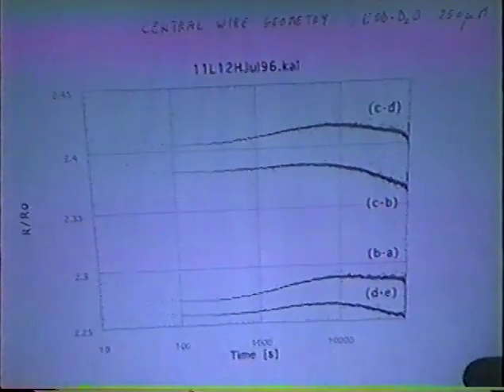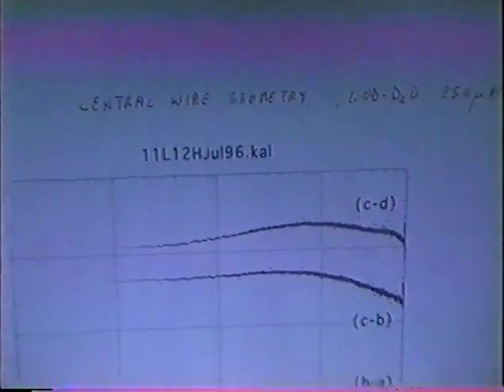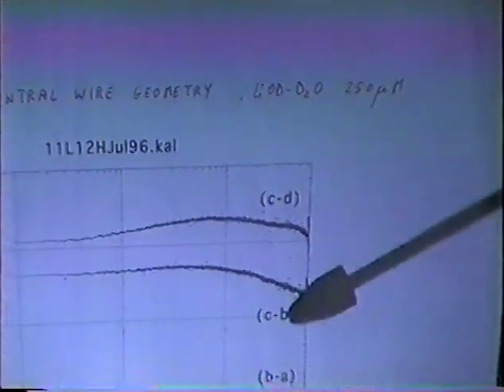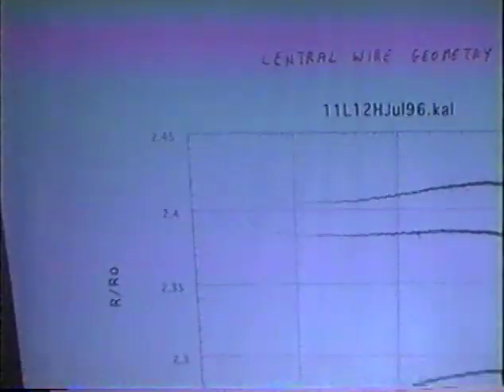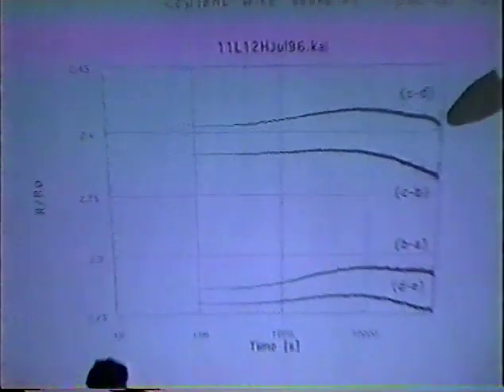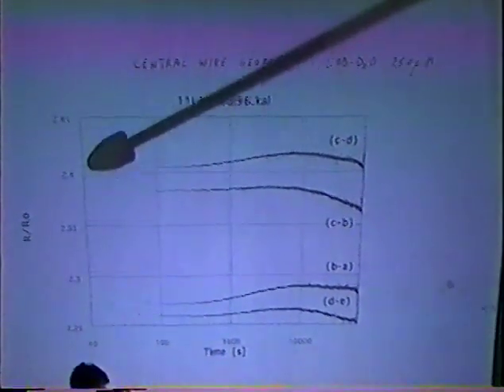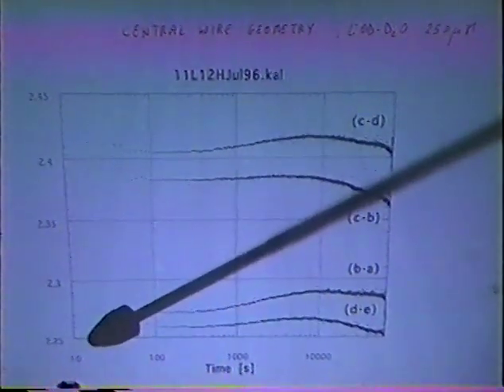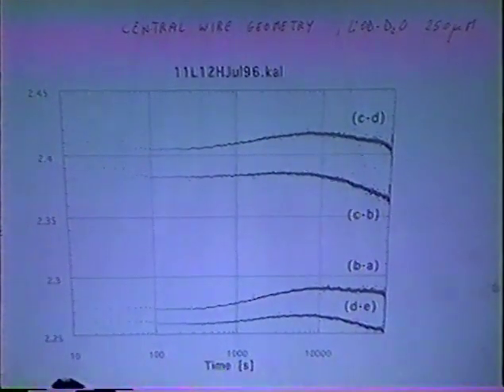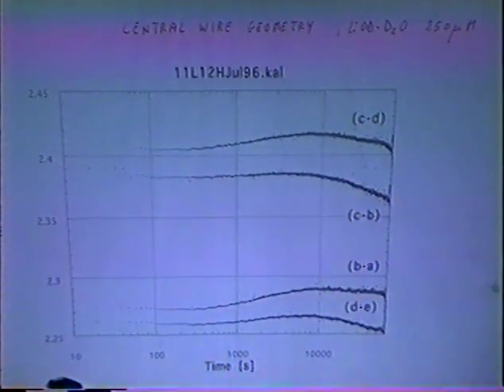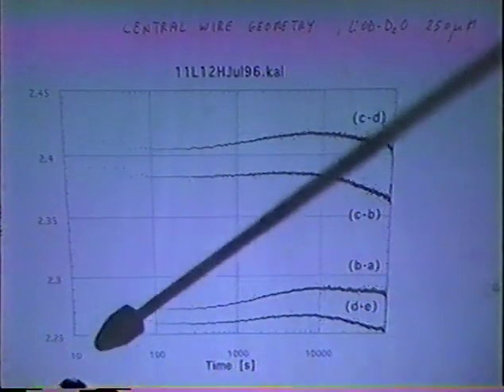This is a similar result, but using the center wire geometry. So this is the center of the wire, and the end. At the center, the loading is much larger than at the end of the wire. So this proves that the center wire geometry and the electromigration is very effective to get large loading, always in logarithm scale.